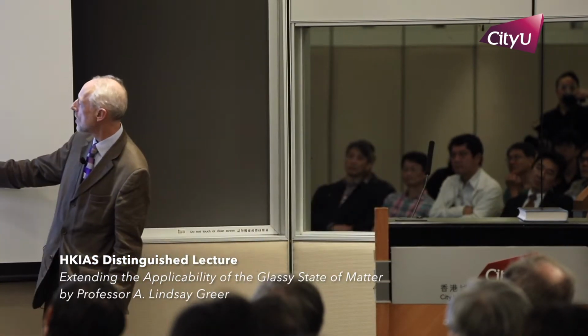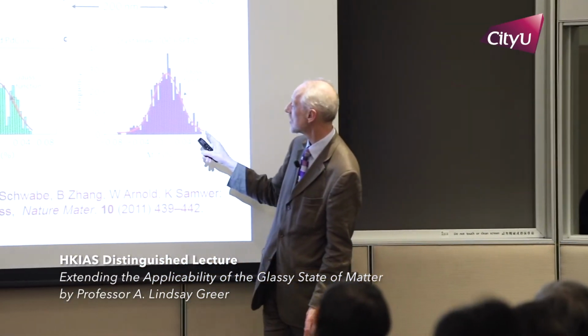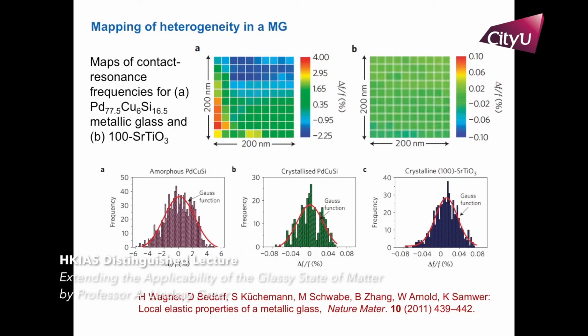If you actually take the surface of a metallic glass, map out local stiffness across the surface, you could do that for the glass, for the material you get by crystallizing the glass, and for a classic strontium titanate crystalline substrate. So the local variation in effectively modulus here is about 0.08% from side to side from the center on that strontium titanate. If you do it on the crystallized material, it's the same sort of range. Look at the glass, it's up to 4 to 6% plus and minus from the central point. Quite a vast range, and odd that that should be true. It seems undeniable that it is heterogeneous. It presumably inherits that heterogeneity from the liquid.